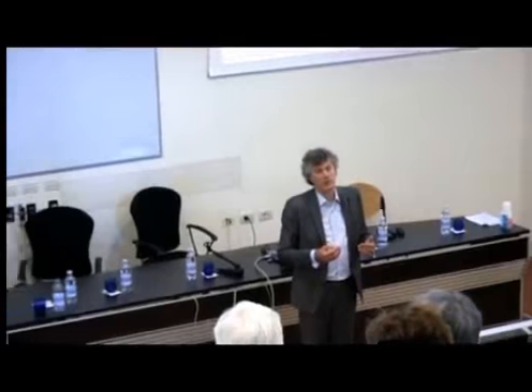Rongsheng Liu, ABB Corporate Research. You have mentioned the thickness of the interface. Then if we go to the other direction, say the area, traditionally people talk about the area effect and so on. Do you have any comments on that? Sorry, the area effect? The area. It's not volume, it's the area along the interface. To comment on the surface area, everything is determined by bonding, proper or improper bonding of your host material. So whatever you do to the surface of your nanoparticle, it needs to rearrange the polymer in the vicinity of the nanoparticle, because otherwise nothing changes.